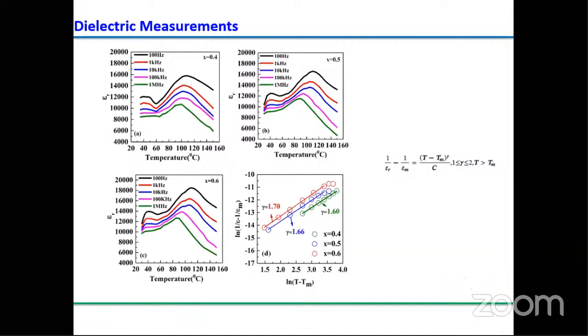So by using this expression, we modified the equation and we fitted for all these materials. And here you can see the gamma value. Gamma we got 1.60 for 0.4 composition, 1.66 for 0.5 composition, 1.70 for 0.6 composition. Okay, if it is a purely conventional material, the gamma value is 1. If it is an ideal relaxer material, gamma is 2. If you have in between, they are called relaxer type materials. They exhibit the relaxer property as well as conventional ferroelectric properties.